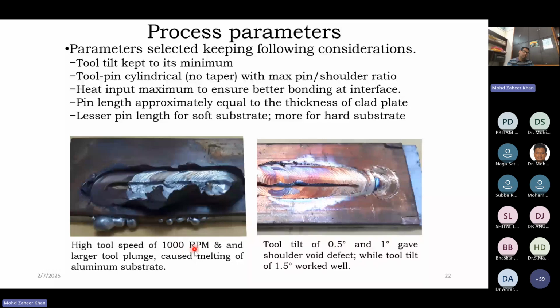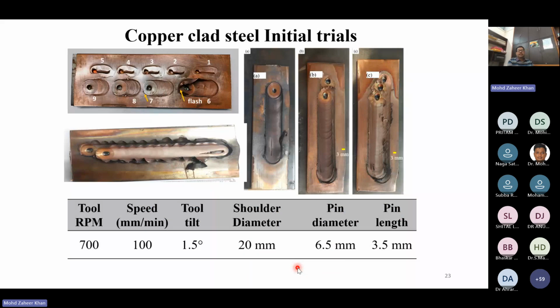However, when the RPM was set to a lower value and the tool tilt was kept at 1.5 degrees, the copper could be cladded on the steel. And of course, there was another important process parameter that had to be set, and that was the tool plunge. If the tool plunge was less, then the shoulder was not completely coming in contact. Whereas when the tool plunge was excessive, this type of flash was coming out, which made it unacceptable. However, after several trial runs, we could fix the parameters.